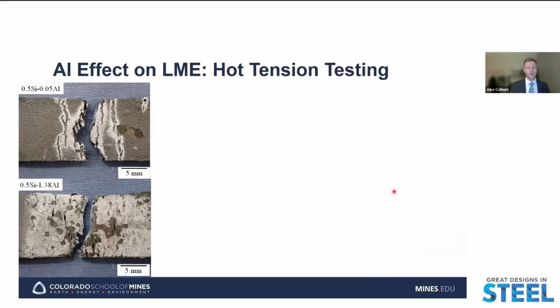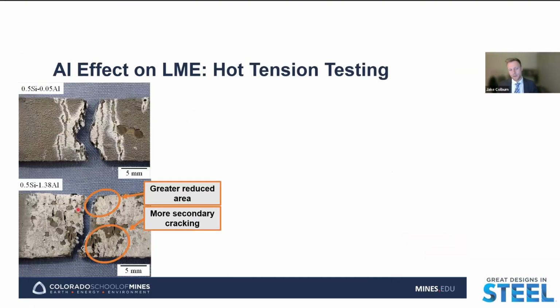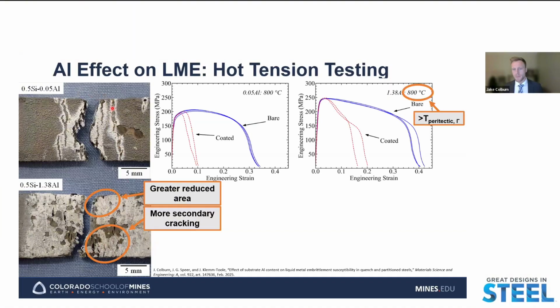And so then if we take a look again at our hot tension test results and take a look at our macro fractographs here, with the low aluminum alloy at the top and the high aluminum alloy at the bottom, tested at 800 degrees C, we see a slightly greater reduction in area, indicative of a greater ductility at elevated temperatures for the high aluminum alloy. We also see more of this secondary cracking in the high aluminum alloy, which are these small cracks that we see appearing on the surface, more so than in the low aluminum alloy, where a majority of the cracks seen on the surface are just cracks in the solidified coating layer.